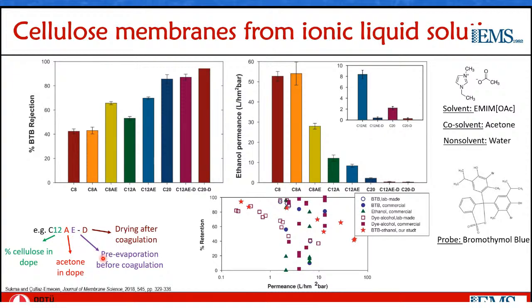E stands for the use of a pre-evaporation step for acetone before coagulating in water. And D stands for the use of a drying step after coagulation. So a number of things that we observed: by increasing the cellulose concentration in the starting solution, we increased the rejection to our probe molecule, which was a dye for simplicity in analysis. So it was just a model molecule, bromothymol blue. By increasing the cellulose concentration, we increase the rejection.